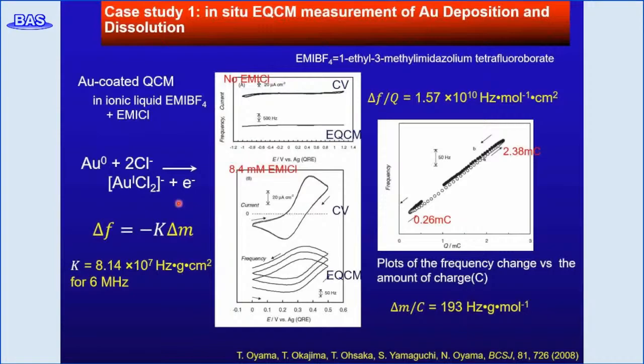In situ EQCM technique combined with CV showed cathodic deposition of Au(I) gold ion to Au metal, and cycling of the potential provides the anodic dissolution of gold from the gold electrode surface and deposition on the QCM chip. The frequency change of the quartz crystal electrode during the electrolysis can be interpreted in terms of rigid mass change.